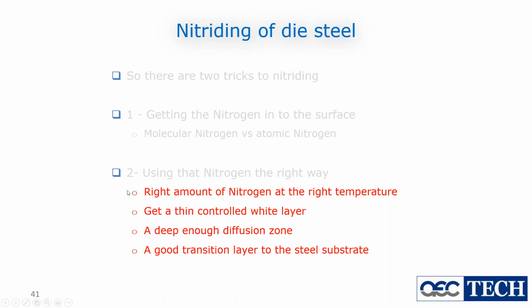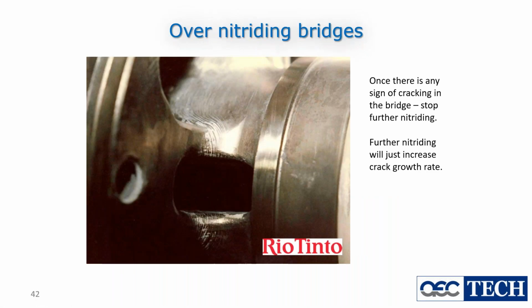And so we need to get the right amount of nitrogen at the right temperature. We need to get a thin, controlled white layer. Thinner the better. If it gets too thick, it will chip off, it'll craze, horrible. We need a deep enough diffusion zone that if there is wear somewhere, there's still some good hard steel behind it. And we need a good transition layer between the diffusion zone and the steel substrate so that it doesn't peel off.